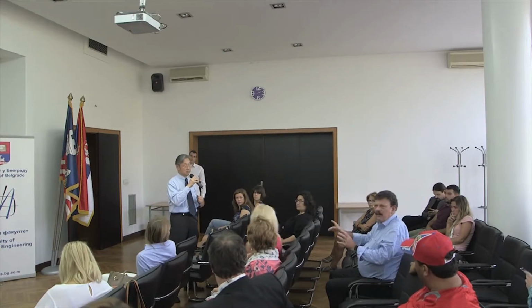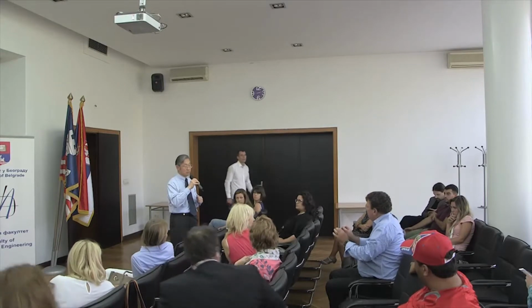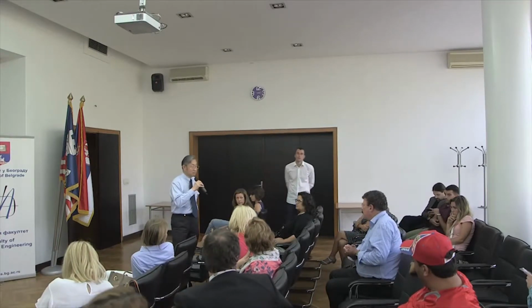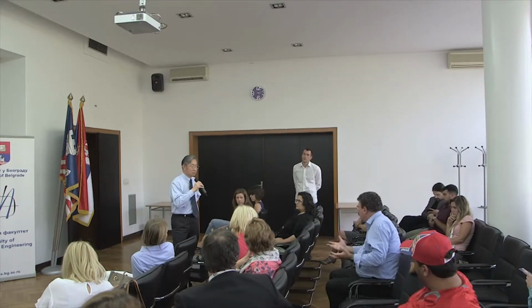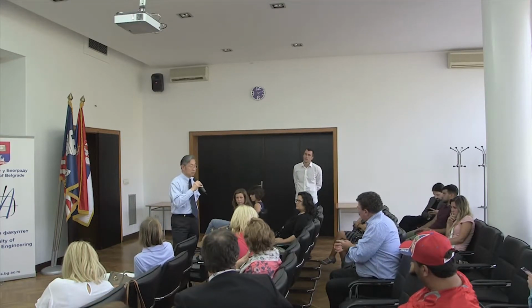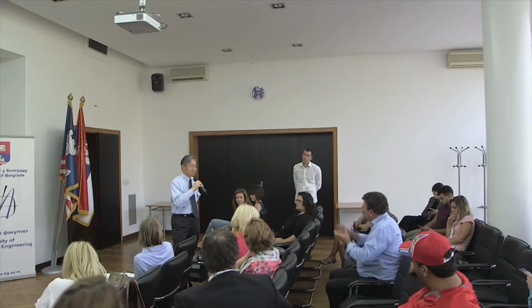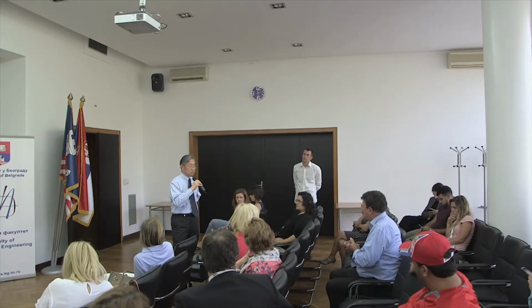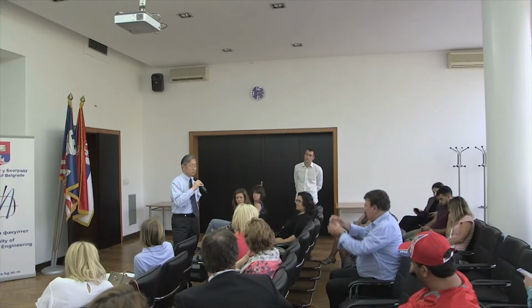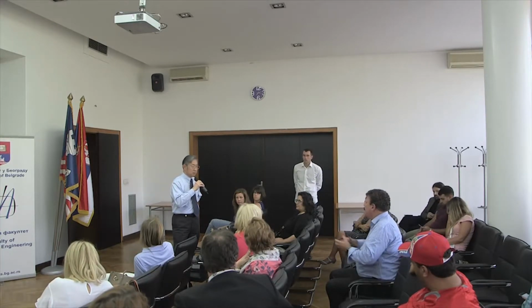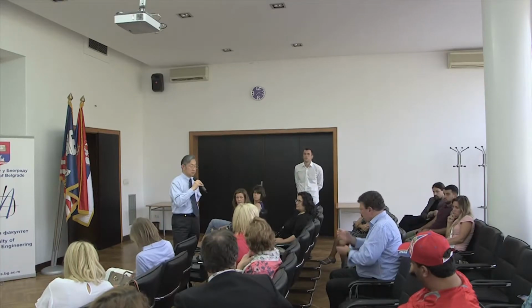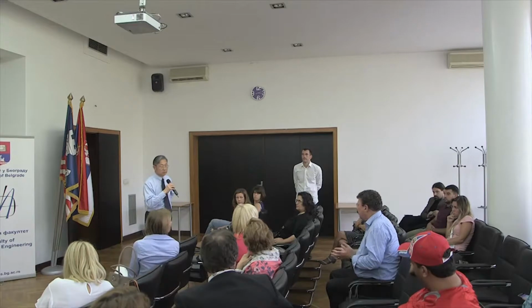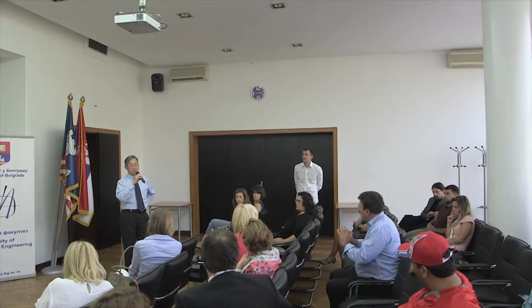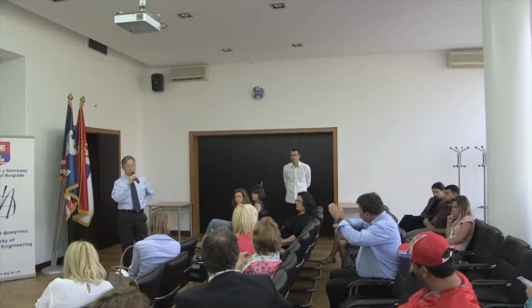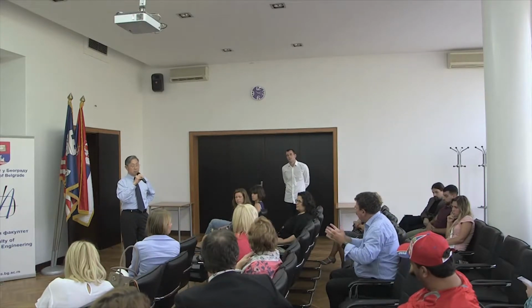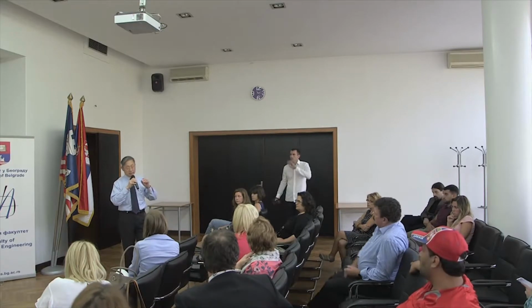Well, can I respond to this? I think mechanistically, everything would favor the surface crack, because it's got more environment and it's much more powerful than the internal crack. So I don't think it's mechanism. Let me say what I think. I think this is purely a statistical thing. You have a large volume and you have a smaller surface, and the probability of finding a larger defect is greater in the volume than it is at the surface. Even though the surface crack is more dangerous, I think that's probably the primary factor that moves the SN curves down. It's statistical.